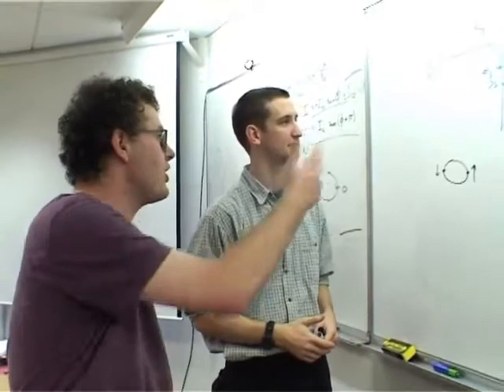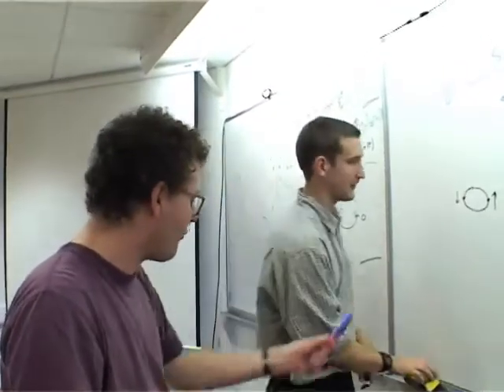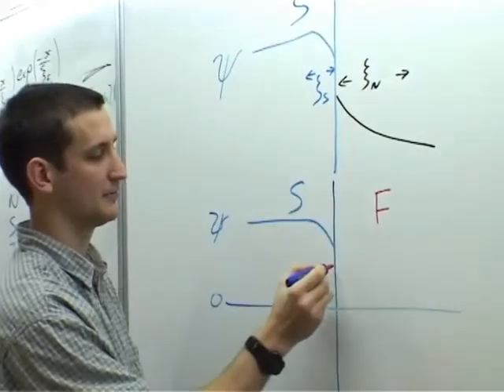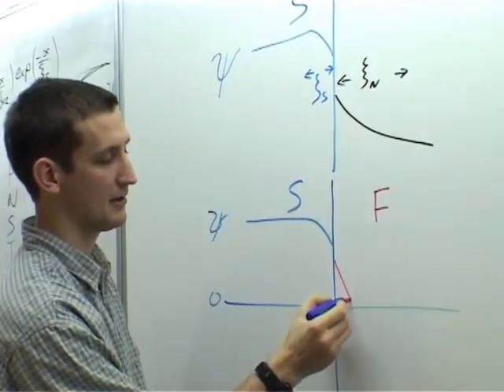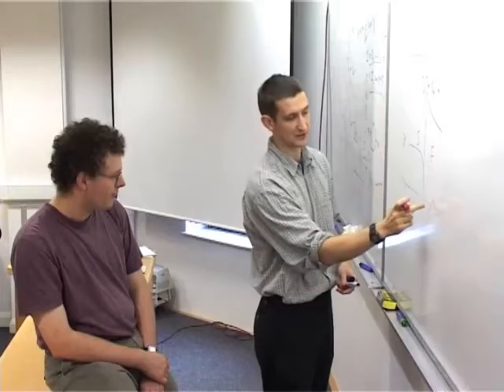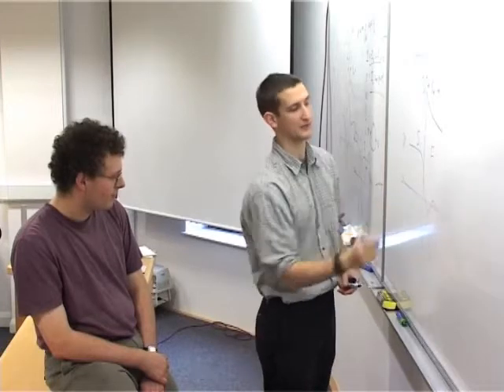What happens if we change the normal metal for a ferromagnet? It turns out, actually, that it doesn't just decay. We get a decay, but we also get an oscillation as the superconductivity is destroyed in the ferromagnet. The wave function is actually changing sign, so down here we have a negative sign.